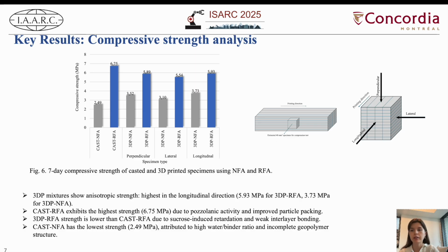As expected, the cast samples with recycled aggregates showed the highest strengths overall due to better compaction and a more monolithic structure. And the 3D printed samples show slightly lower strengths, especially in the lateral direction due to the layered structure and presence of interfacial voids. So strengths varied depending on the loading direction, with the highest values recorded along the printing path. Recycled aggregates performed well in both methods, demonstrating their strong potential for structural application in 3D printed construction.